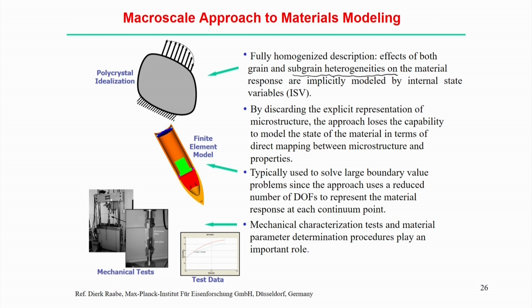The second point is that by discarding the explicit representation of the microstructure, the approach loses the capability to model the state of the material in terms of the direct mapping between the microstructure and the properties. So when we try to idealize the polycrystalline behavior, or the heterogeneity behavior in the single crystal, and represent it as a single polycrystalline behavior, as an aggregate, the individual heterogeneity behavior can be lost, and we use some aggregate behavior at this scale. It is typically used to solve large boundary value problems, since the approach reduces the number of degrees of freedom used to represent the material response at each continuum point. So, this is the first idealization, the polycrystal idealization.